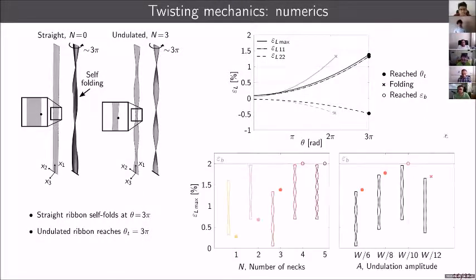So now what we do is to actually use this model for the undulated ribbons and try to test a bit what is the influence of the various parameters. So what we can see is that this is the maximum principal strain as a function of the number of necks. And we can see that increasing the number of necks, we increase the maximum principal strain that we achieve. And in particular, for number of necks greater than or equal to 4, we exceed the elastic limit. Okay, so that's not something that we want. And we know that our material, after exceeding the elastic limit, pretty much breaks.